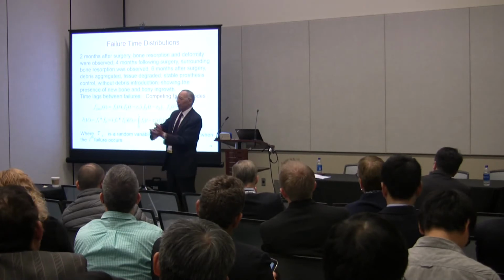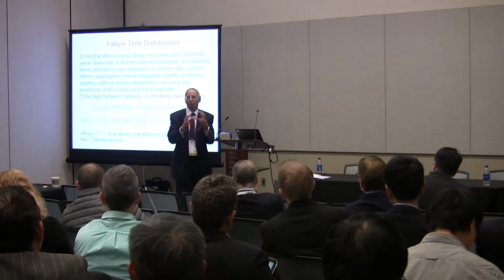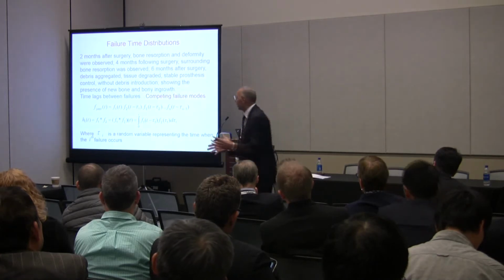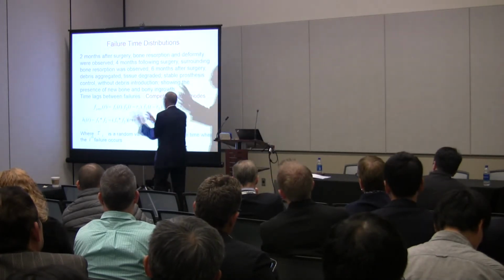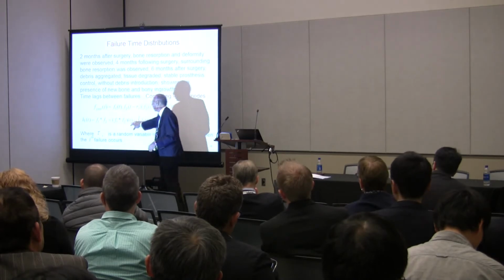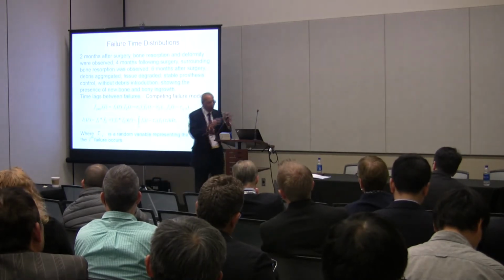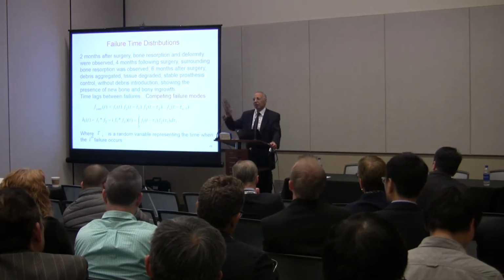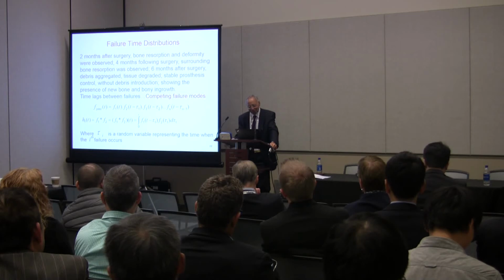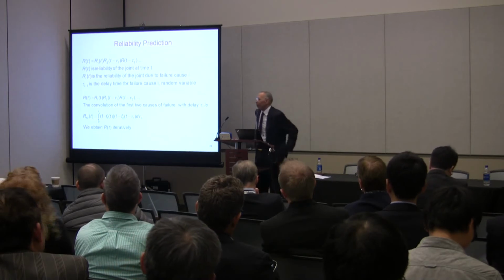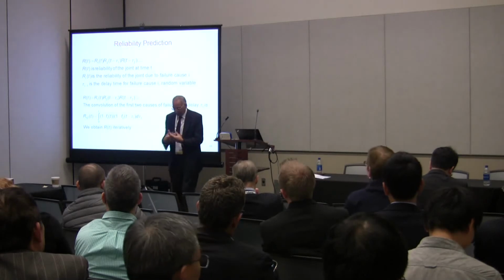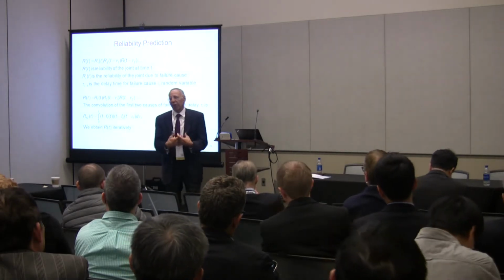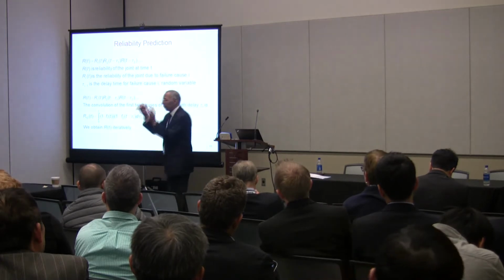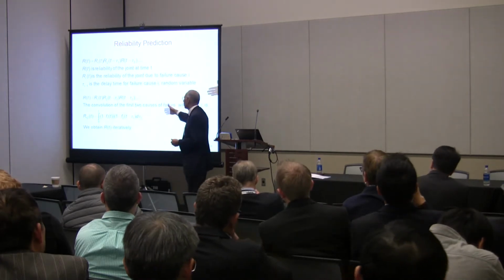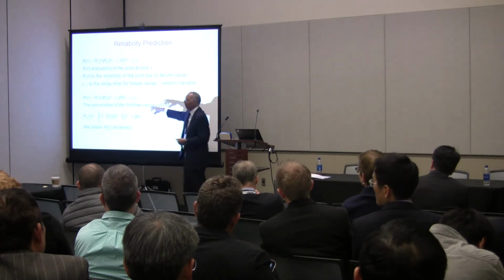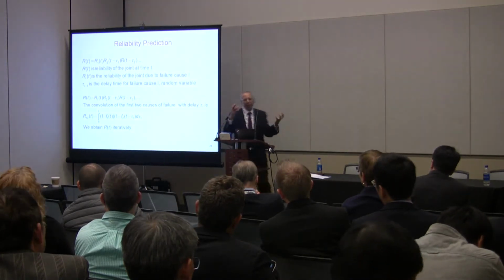Forget even the joint work I'm presenting. If you want to mathematically solve this problem by itself, it would be a challenge. So you do convolution. Here's an approximation: you take every pair at a time and do convolution, and then convolve the next one, and so on. That's one way. I have no solution for this problem, by the way. This is the future, so I don't have an answer for that. So we can do this: we say the reliability of units that are connected and compete in failure modes, we call it competing failure mode mechanisms. The reliability is the product of the reliabilities of the individual cases. And you do the same as I mentioned to you, and you worry about looking at the convolution of reliability functions or PDFs if you have enough data.